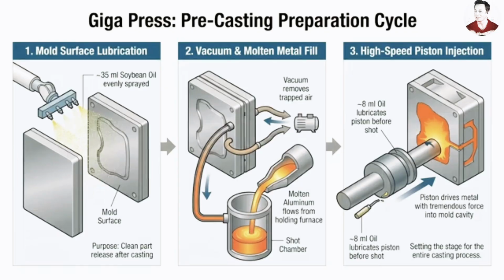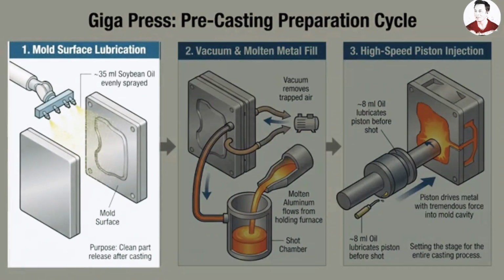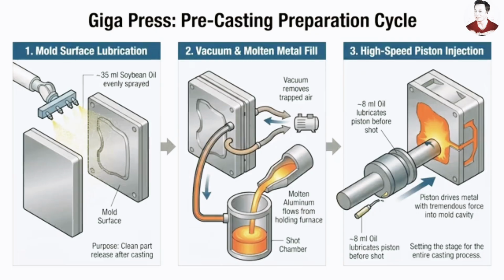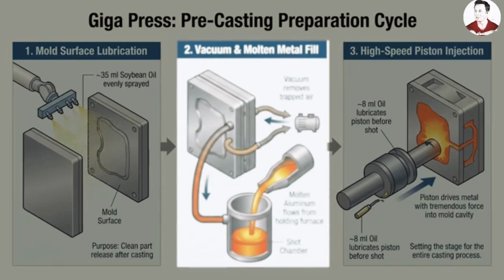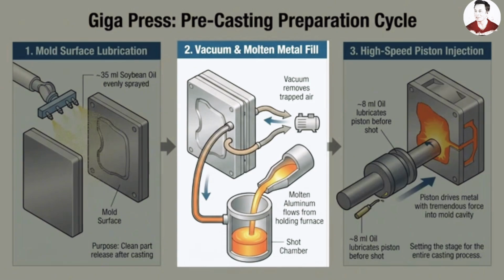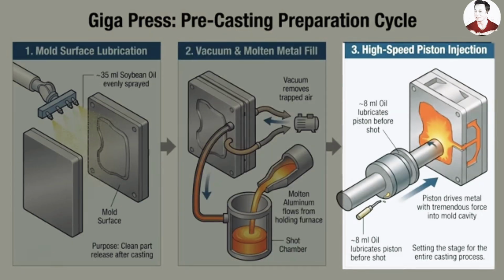Before every casting cycle begins, the Giga press coats the mold with a thin layer of lubricant. A robotic arm sprays about 35 milliliters of soybean oil evenly across the mold surface, much like greasing a baking pan, so the finished part can be released cleanly afterward. The system then creates a vacuum to remove trapped air before molten aluminum flows from the holding furnace into the Giga press's shot chamber. Finally, a high-speed piston, itself lubricated with roughly 8 milliliters of oil before every shot, drives the molten aluminum into the mold cavity with tremendous force, setting the stage for the entire casting process.